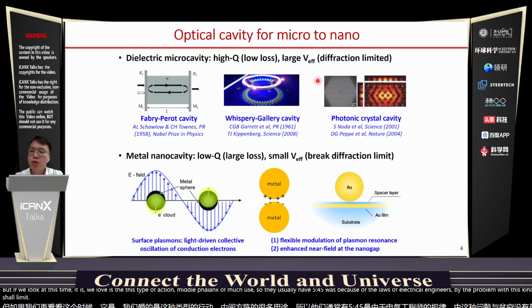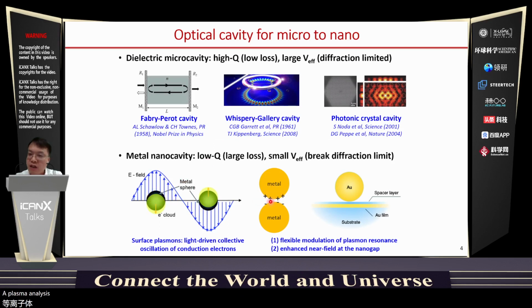To overcome the problem of this diffraction limit, we can resort to the so-called plasmonic nanocavities. They are made of noble metals. By exciting the localized surface plasmon resonance in those metallic nanoparticles and coupling those nanoparticles together, we can form the so-called plasmonic nanocavities with very, very small mode volume. A typical example is this nanoparticle dimer. Of course, you can also have a larger variation, that is, the particle-on-film system.